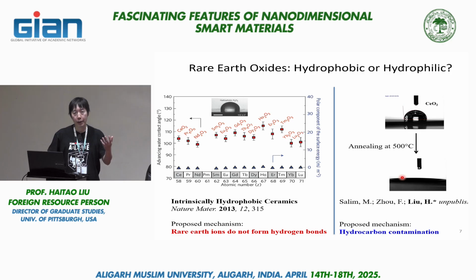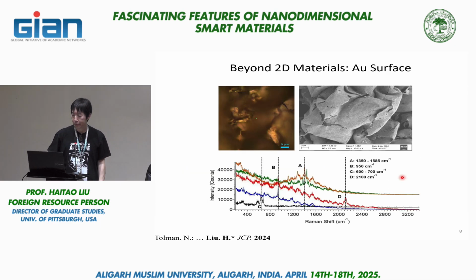And if you are not paying attention to the experiment and understand the chemical principle behind it, you may come to the wrong conclusion. So more recently, we showed that the same kind of process happens on gold surface. We prepared porous gold surface, and this is an optical microscope, and this is a scanning electron microscope. The intention there was to get a sense of what kind of hydrocarbon materials we're dealing with. And also, at the same time, the porous gold, as you may know, has a lot of interesting application in SERS, surface-enhanced Raman spectroscopy.